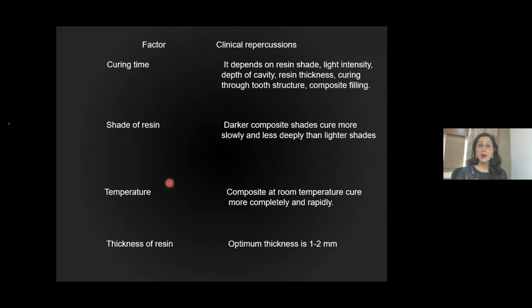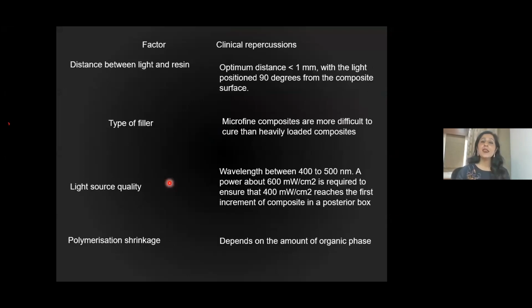The composites at room temperature cure more completely and rapidly, although there are so many advancements in this also. Thickness of resin should not be more than 2 millimeters. The distance between the light and resin should be less than 1 millimeter, and the light should be positioned 90 degrees on the composite surface. If you're using microfine composites, I have not talked about them, but microfills are also there on board. If you're using them, remember that they are very difficult to cure. So give an increased curing time for them.